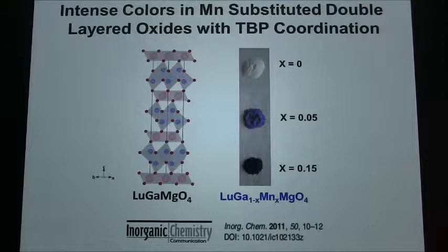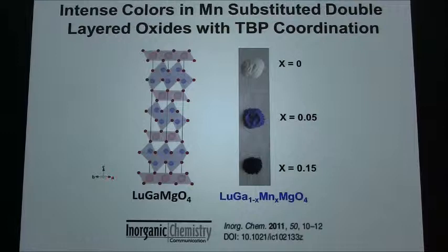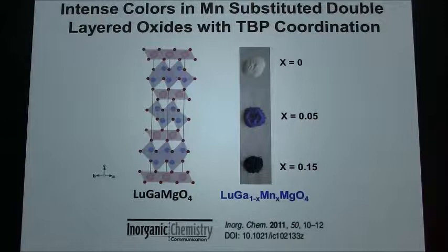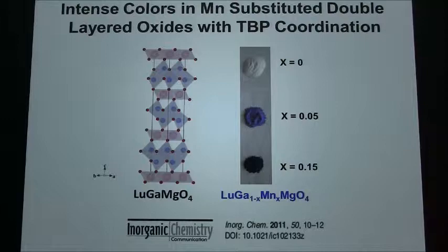We also proved that blue color can now be designed by stacking different crystal structures, again with five-fold coordinated manganese, in another material. We actually designed it to create blue colors. By putting in a small amount of manganese, as you can see, it becomes purple to blue, whereas without manganese the compound is only white. When you increase the manganese, it becomes darker blue. So we can now understand where the blue color comes from, and how we can design colored compounds using this type of chemistry.